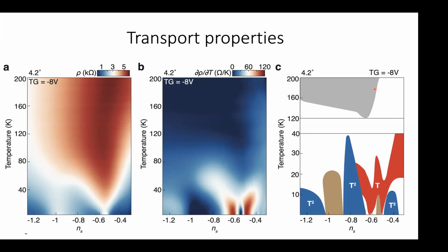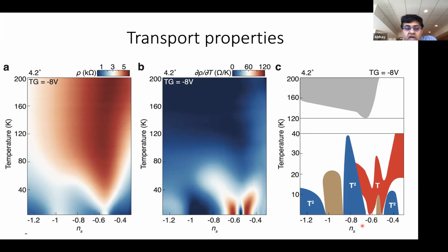For this quantum critical point, do you have any speculation from what phase to what phases? At this point, this is still speculation. We believe that the insulating phase is actually an antiferromagnetic insulator. And there is some speculation about whether there's actually some ferromagnetism in the metallic phase. We are looking for signatures of anomalous Hall, and we have some signatures, but that's still not conclusive yet. So you mean these 2 quantum critical points may be 2 different magnetic phases, one antiferro, the other maybe ferro. But it's also a metal insulator transition.